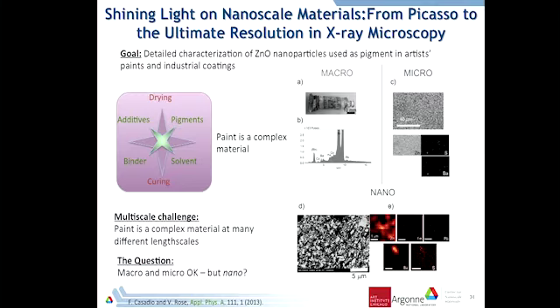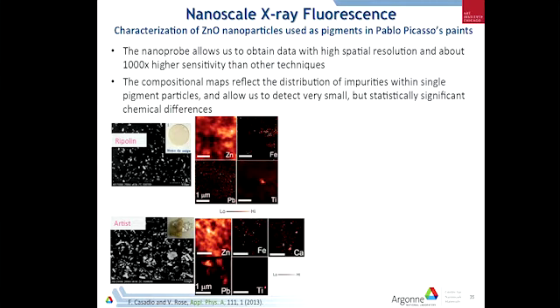And the paint that was looked at was white paint, and the pigment that's in white paint is zinc oxide. And so yes, we're going to see zinc and we're going to see oxygen there. But what distinguished them are very small trace amounts of different elements, such as, for example, lead or titanium, iron. And those are distributed differently in the different types of paint flakes. If we look at the Ripolin paint or the artist's paint, you can see zinc everywhere because it's zinc oxide. I'd hope you'd see that.